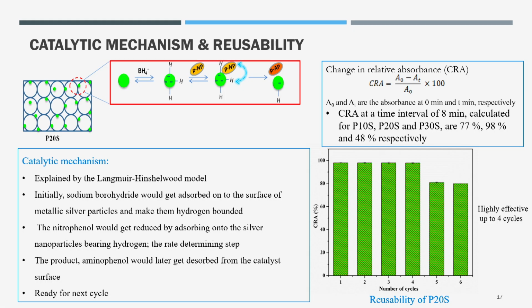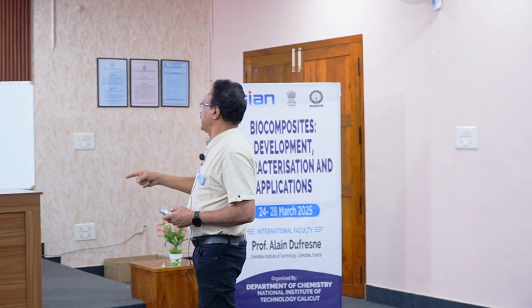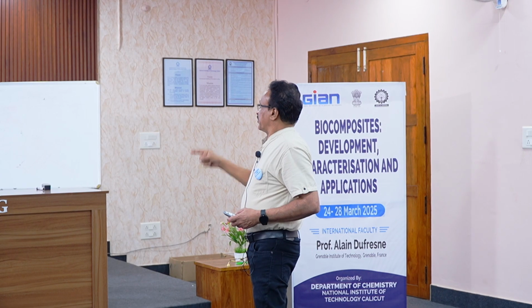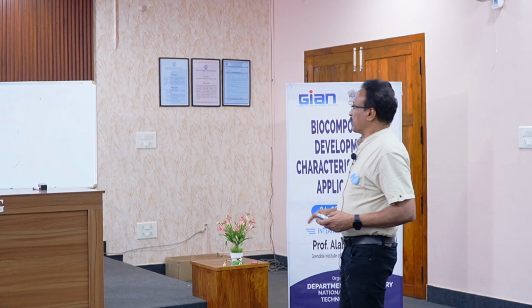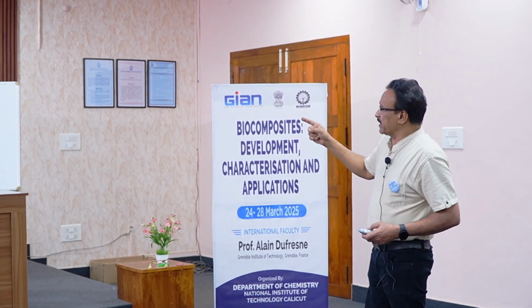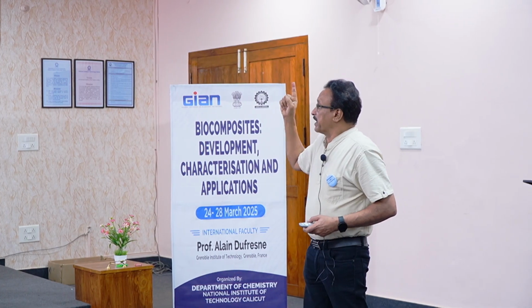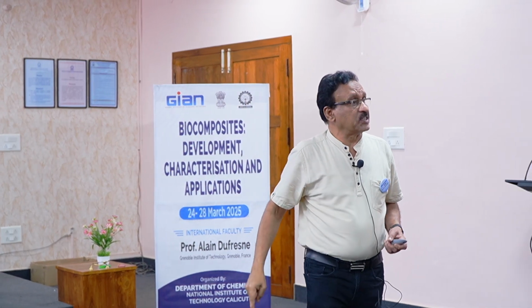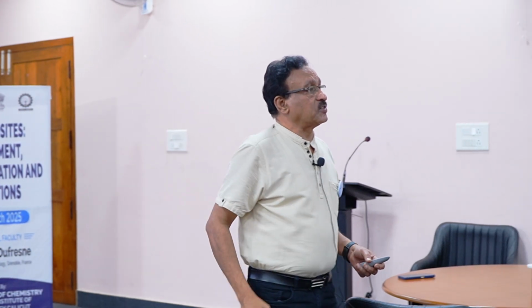That quantitative evidence can be obtained from an equation. Again, visual evidence: the change in relative absorbance can be computed, which is very extensively used by researchers. This is called change in relative absorbance, CRA, calculated at a time interval of 8 minutes. You can see that for the second composition, 98% of absorbance change is there. That means that system is highly efficient to execute this catalytic activity.